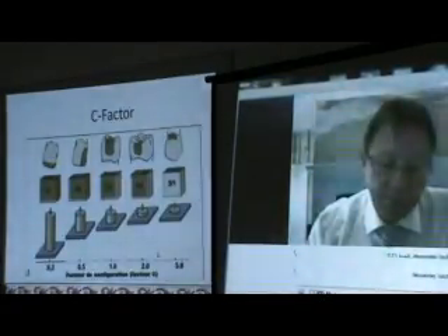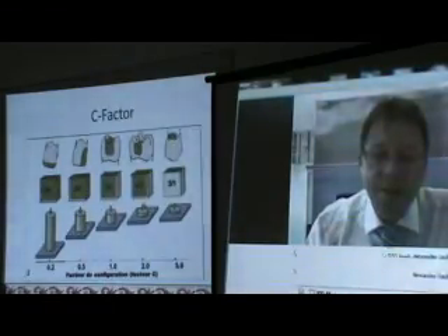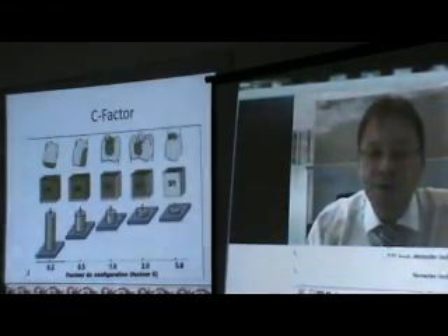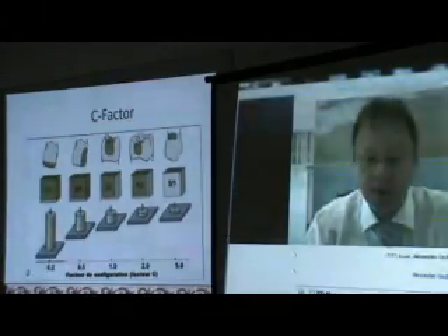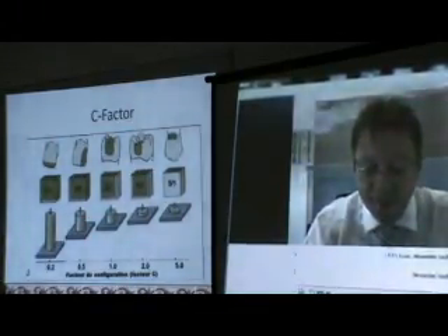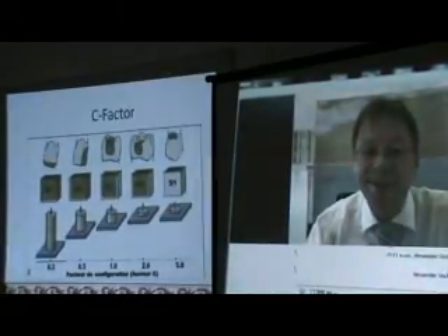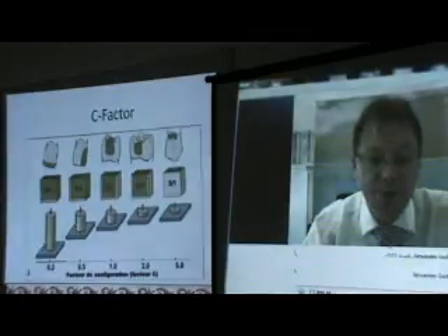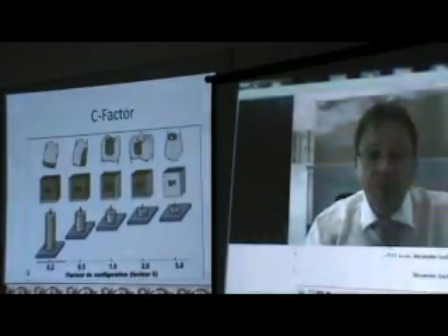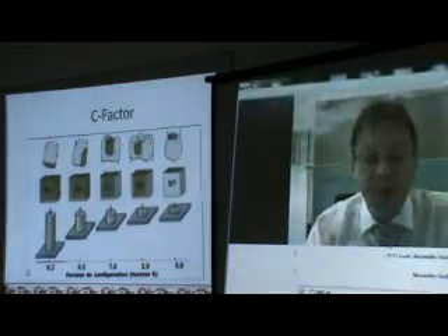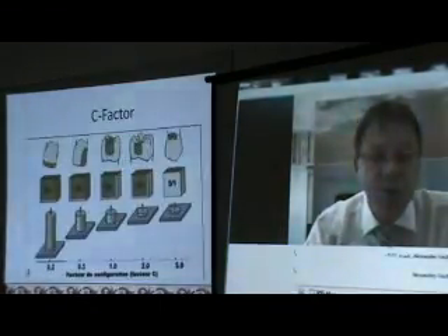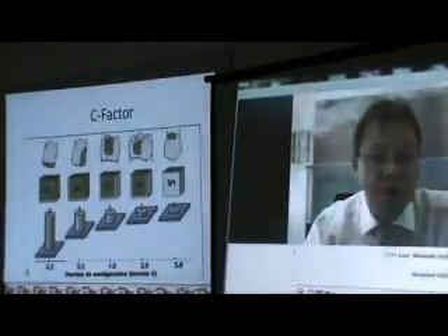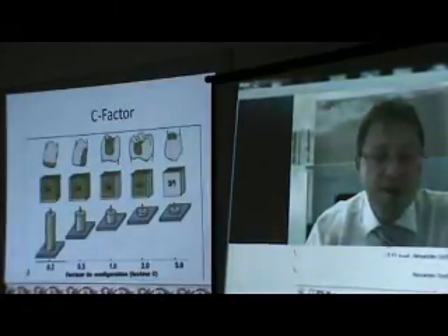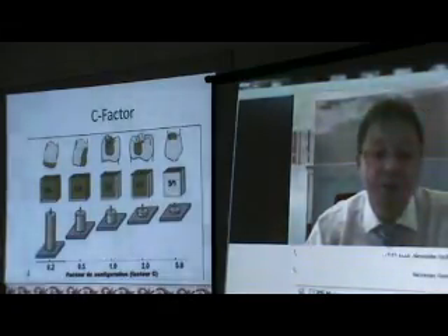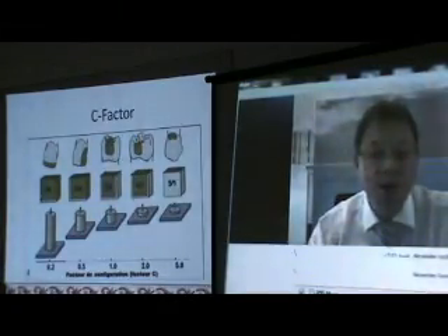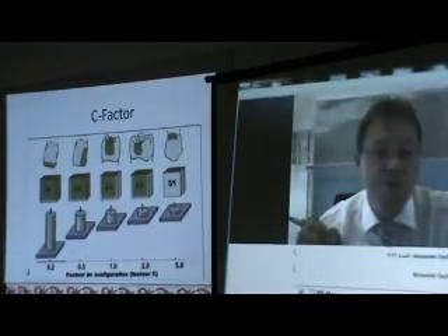Now, the result of this is that if you have a lot of bonded surfaces, of course, like in the case at the very right, in class 5, there it is very rigid. So the more bonded surfaces you have, the more rigid it is, the more important it becomes that you use a composite with a low shrinkage stress value. So as soon as you have 2, 3, 4, or even 5 bonded surfaces, please check that you use a composite with a low shrinkage stress.